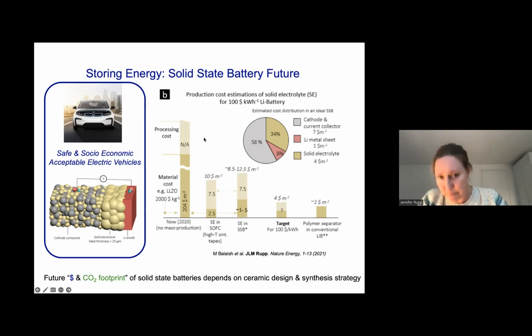And there have been some rough projections in numbers where we can see that currently, if you just take the analogous calculations known from other ceramic tape making, you have to end up somewhere at about $4 per square meter to be quite close to the polymer separator, which is currently already at about $1.8 per square meter. So currently the tape production is quite expensive and quite challenging. And the main reason for this is that 75% of the costs are really related to the processing. So it's not so much the raw material, it's all the processing costs.